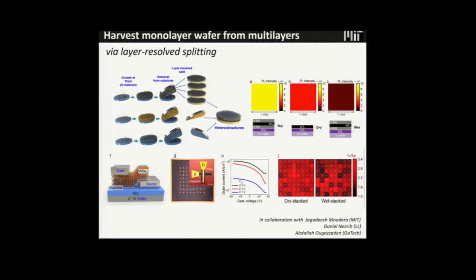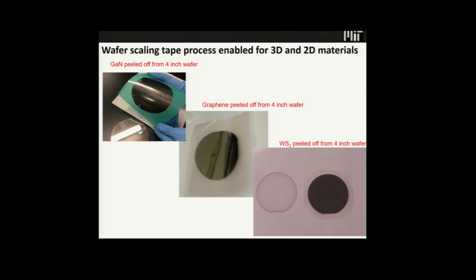That was dry stack. That was wet stack. As you can see, there's a clear difference. So wet stacking gives you a lot of variation in devices, but dry stacking makes a very uniform device all over the arrays. So our goal is what? Our goal is to mix and match the 3-dimensional flexible materials and 2-dimensional materials, all of them together. So then we can have some more freedom to design the heterostructures.